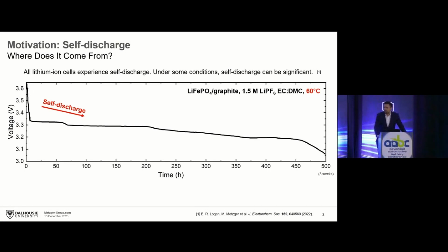So, for us, self-discharge is really something that was driving us crazy in our laboratory. So we do a lot of tests on battery cells that operate at high temperatures. We do a lot of storage tests of battery cells at elevated temperatures. And of course, every lithium-ion battery in the world shows self-discharge. But under some conditions, the self-discharge rates can be really fast. And obviously, this is a huge problem for really any applications where batteries are used. But of course, also for automotive batteries, right? That's something we want to avoid.